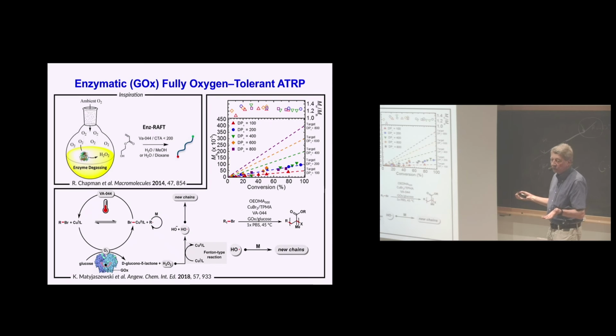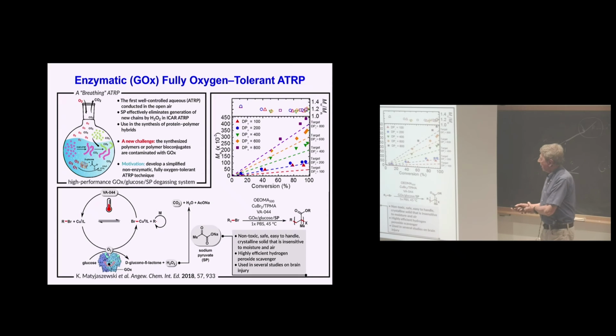So what to do? You can go back to maybe a biochemistry book, and you could see that sodium pyruvate is used in the Krebs cycle or cell respiration cycle. So pyruvate reacts very quickly with hydrogen peroxide, and they would form carbon dioxide, water, and acetate anions. This is very similar to the breathing process because we work with these reactions in open air. Oxygen comes in, CO2 gets out. Oxygen comes in, CO2 gets out in the presence of pyruvate.